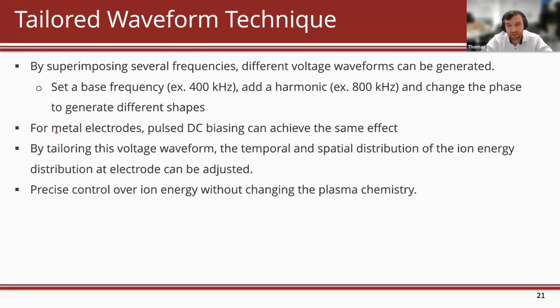If you're using metal electrodes, I'll explain this in a minute, you can basically use pulse DC to achieve this fine energy control. So you might still be at 400 kilohertz, but you have a sharp DC pulse or a longer DC pulse. So I'll show you that in a moment. And by tailoring the waveform, you can actually control what the energy distribution is. And you can do that without changing the plasma chemistry because you're just changing the voltage, okay? You're not trying to impact how much current is there. So usually in tools that have tailored waveform biases, you still apply a different high frequency in order to really get a strong plasma, so maybe 60 megahertz or 40 megahertz, and use that to raise or lower the ion flux.